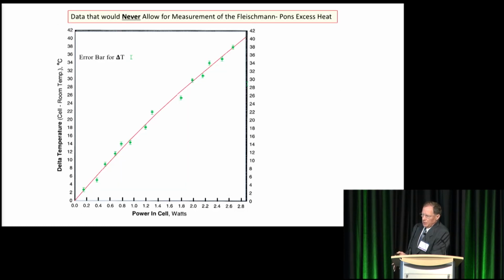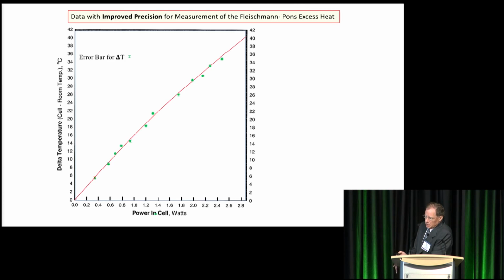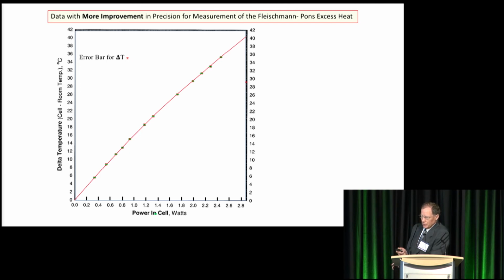This is a hypothetical data set for the difference between the inside of the cell and the outside chamber. And this would never work. The precision here is just too poor. You can improve the precision and approach the actual calibration curve shown in red, but these points are still too far away from the curve. So with further work, you can improve the precision. You're not changing the accuracy, but you are improving the precision and giving yourself confidence that if any data point is off of this curve, it's the real thing.